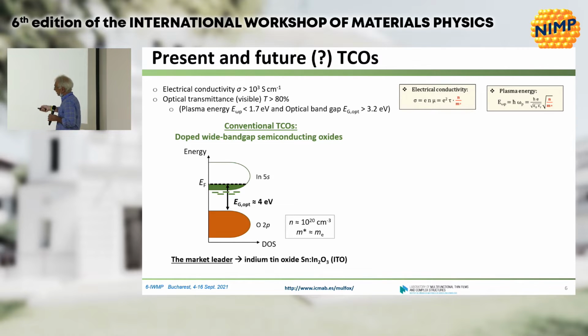Indium oxide is a transparent material with a big gap between the oxygen band and the indium empty 5s bands, and then doped with tin. You get some donor defects here and some electrons in the conduction band. So you get something with a large gap here and some electrons here. This is going to be potentially a transparent metal. In fact, it turns out that indium oxide can be doped to get a metallic behavior and still be transparent.